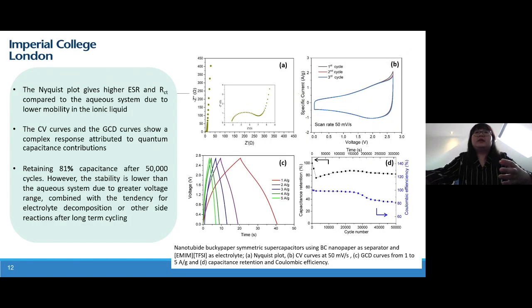After achieving high performance in the aqueous system, the other way to improve the energy density, not only using pseudo-capacitive material, is by changing the electrolyte. Using an ionic liquid can improve the potential window of the cell, and that is the reason it can increase the energy density. However, we have to know that the ionic liquid itself has lower mobility, which can cause a higher internal resistance and charge transfer resistance in the system compared with the aqueous one.